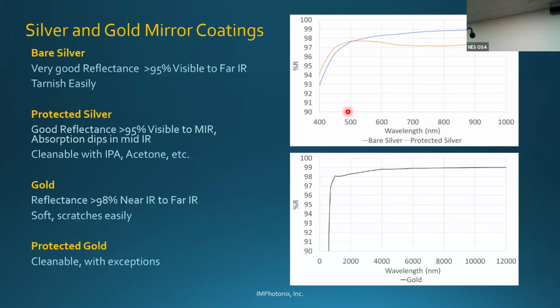Question? Yes. Not an expert on this, but can you vary the substrate that you're making a reflector out of so that some of these metals stick much better? Well, we do. Gold is not deposited just as gold. There's a binder layer that's always put underneath. Usually it's chromium. And that binder layer will help that gold stick to any metals or glass. So usually chromium is what we use for a binder layer. Or you can actually use an alloy too. Nichrome will also work as a binder.